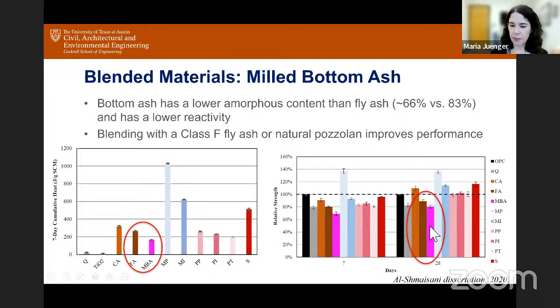If we test it for compressive strength, again, this is 28-day strength, not 90-day strength, if we look at the Portland cement, black, being the control, the Class F fly ash and the milled bottom ash are slightly lower than the Portland cement. They're somewhat lower at 28 days. They are still greater than 75%, and the Class F fly ash is about 85%. So again, if we were just going to take this particular milled bottom ash and call it a replacement for fly ash, you might say, it's not really good enough. Our bar for fly ash is pretty mediocre. It's not meeting the mediocrity standard.